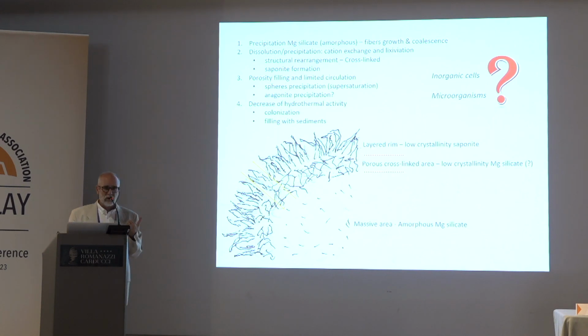But here we discover it is clay, but really it is not clay. The tower is formed by amorphous silicate. We don't know really how they form, but we think it's not biogenic. Our evidence says it's purely inorganic, and the presence of clay is quite limited to the external part. So first is the precipitation of the filament. This filament grows and then coalesces and modifies the structure, and then the fluid flowing in contact with the filament produces additional cation leaching that made the rearrangement of the amorphous silicate into this area.